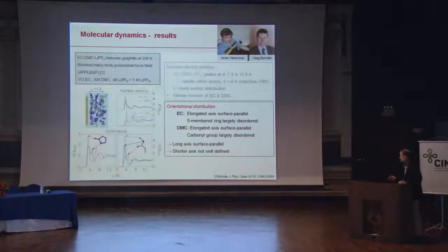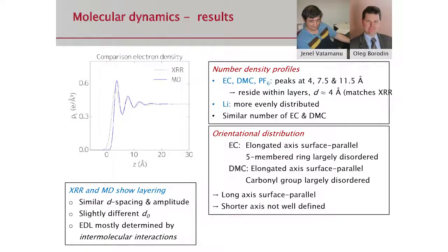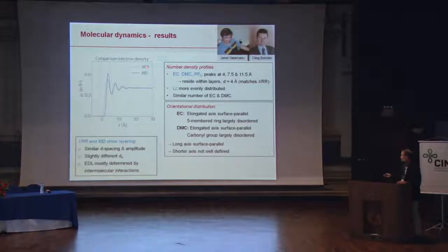Okay, so that's great, but one of the advantages of this is we can take this simulation and directly compare that to our experimental data. And that's shown here. The red is the data we just took, and the blue is the molecular dynamics simulation. We had to adjust for the roughness in the substrate in getting the MD, so that's why some of the peaks are a little bit smeared out. But if you look at this carefully, you see there's incredibly good agreement between the MD and the X-ray reflectivity.